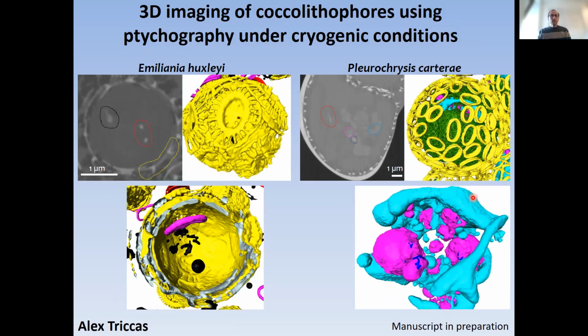So these are examples of data sets that we collected from Emiliania huxleyi here on the left and Chrysotila carterae on the right. This is a slice from the 3D volume, so just looking at the cross-section of the cell. We can see on the outside mature coccoliths. This here circled in black is a compartment, and it's brighter because it contains calcium ions. And we see here circled in red a forming coccolith.